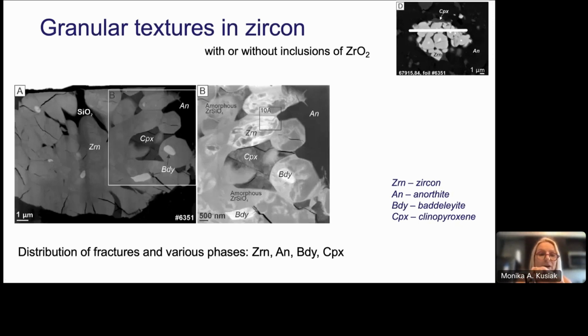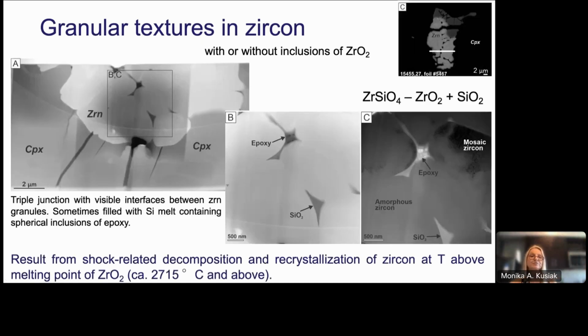Many grains showed granular textures. With this texture, we had either zirconium oxide inclusions or not. So sometimes they were not present. And as you can see, we have various phases: zircon, anorthite, baddeleyite, and clinopyroxene, which are present here. And as well, we have an amorphous phase of zirconium silicate present in this granular texture of zircons. And in the triple junctions, which are visible interfaces between these zircon granules, sometimes we could have filling with silica melt, and this silica melt sometimes contained spherical inclusions of epoxy.